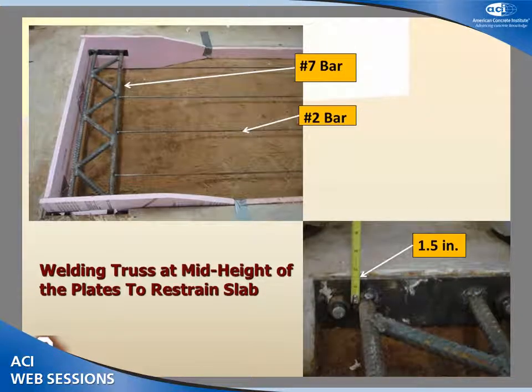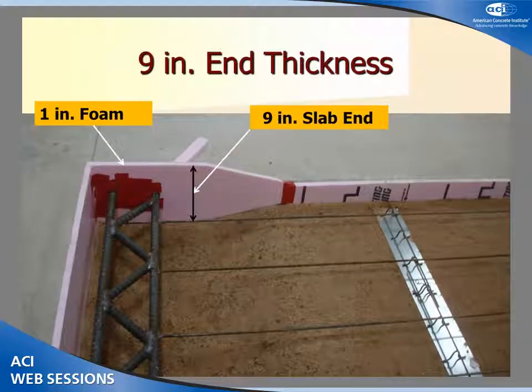So these steel trusses were welded at mid height of the plates, and also we welded 4 number 2 bars based on the ACI 360R minimum required temperature reinforcement. The ends of the slab specimens are 9 inches. This way we restrain the slabs by casting concrete all around the steel trusses for 9 inches. So this is the end of the slabs, and also we used 1 inch foam as a form, and also as a divider between our slab specimens and the existing slab.